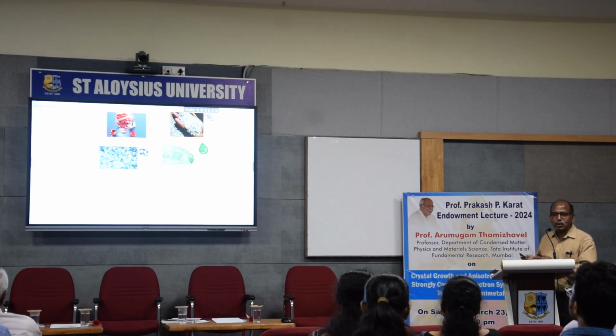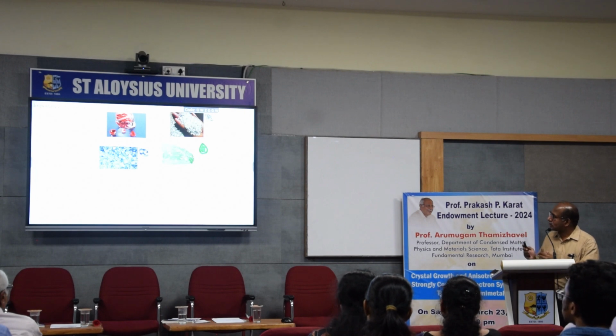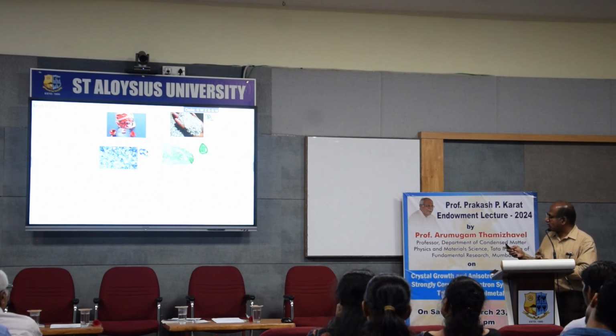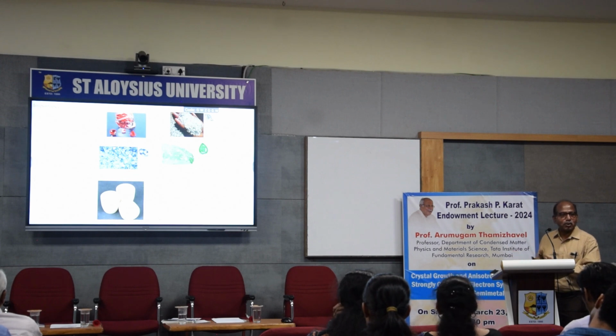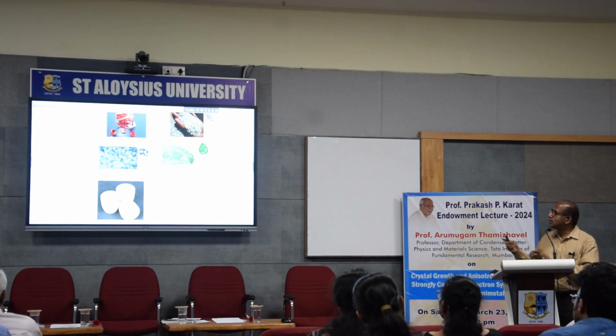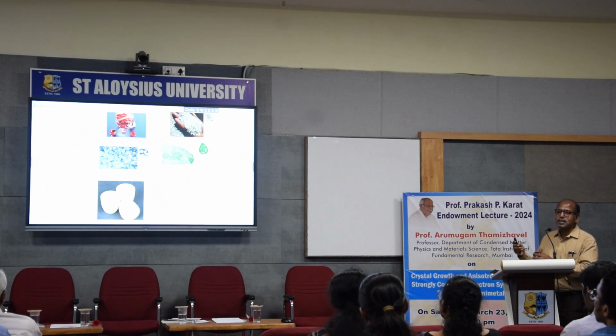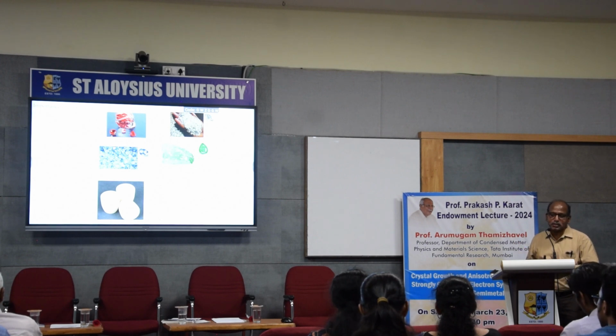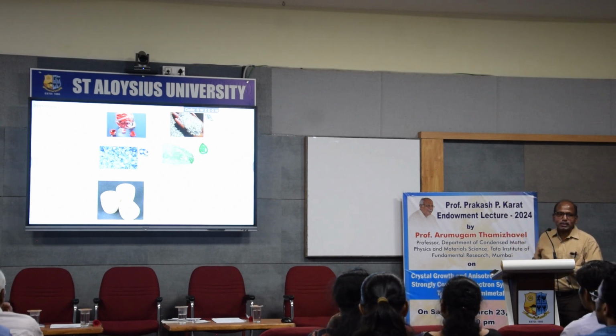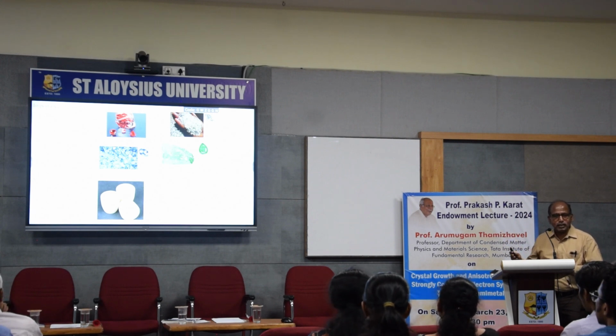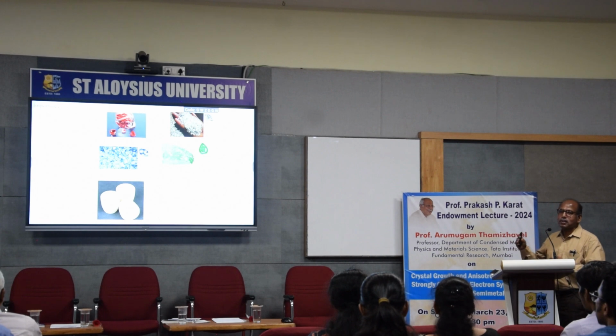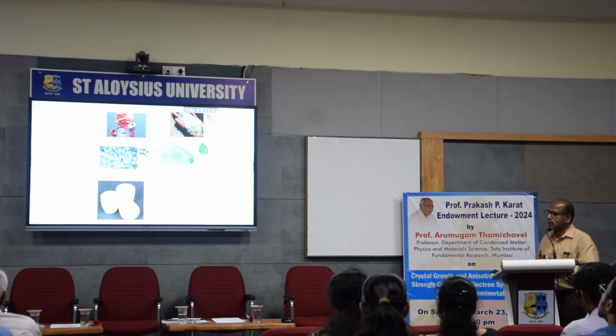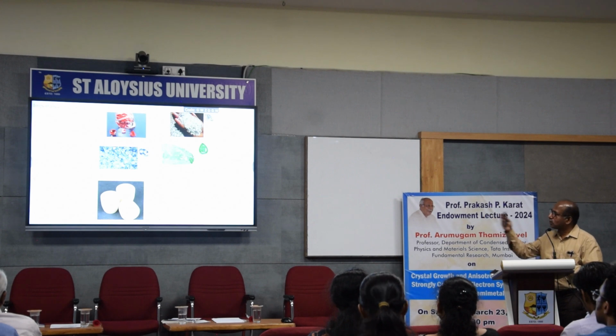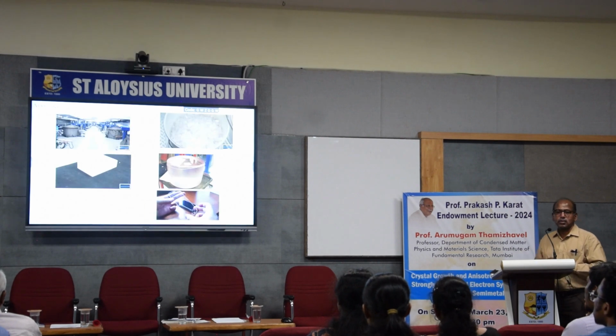These are crystals. If you cut and polish them, you get this kind of eye-catching jewelry. But this is nothing but aluminum oxide. If you look at it in the polycrystalline form, you will see something like this, as I have shown you. These are alumina crucibles, which are used to hold samples up to high temperatures. This same material, when you grow it as a crystal with some doping, has beautiful colors, and when you cut and polish, you can have very nice looking samples. The same sample, if it is in a polycrystalline form, will look like this white stuff, which is shown here. And crystals are not used only for aesthetics.